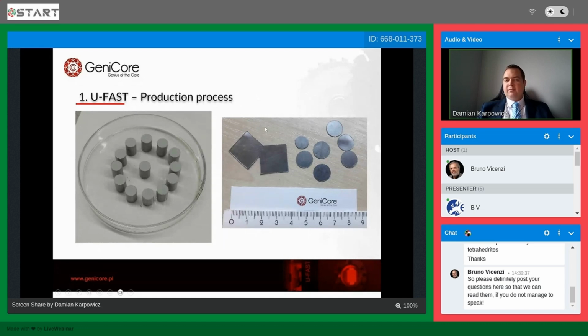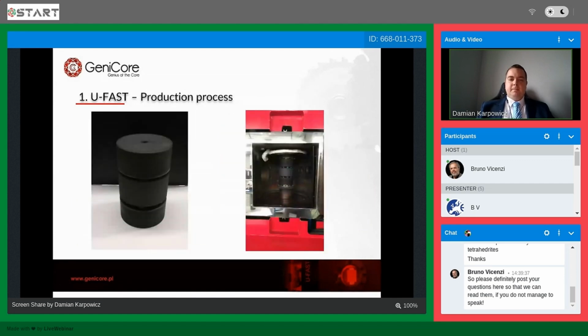We also use the graphite foil, which allows us to separate the sample from the graphite mold, which increases its lifetime significantly. So we can assume that one mold can withstand more than 100 processes if designed correctly. So UFast and SPS technology is not only the production of single samples, which is often misunderstood. We are able to design and produce molds which allow us, like in this example, to produce 65 pieces of RNGN cutting insert, which is used for Inconel machining.